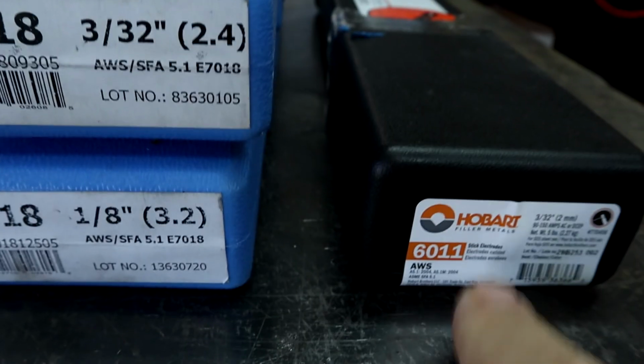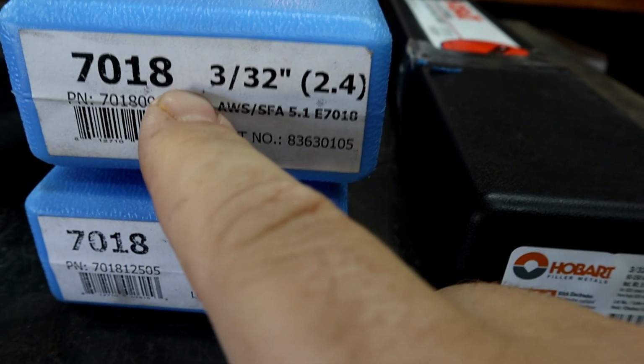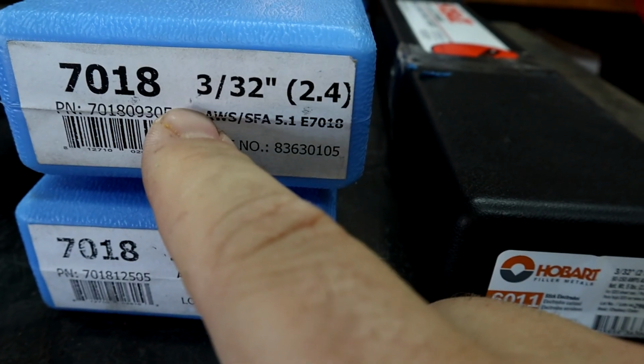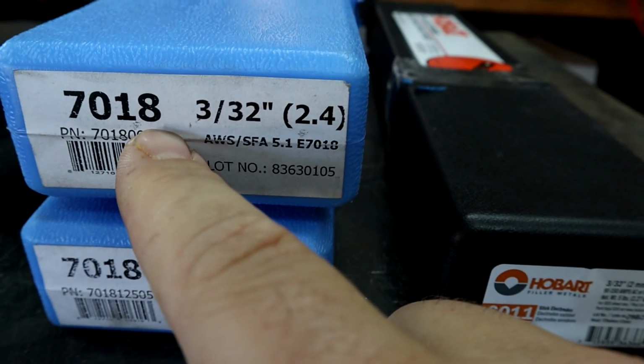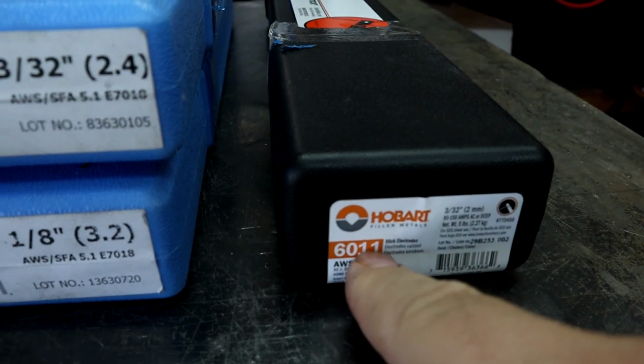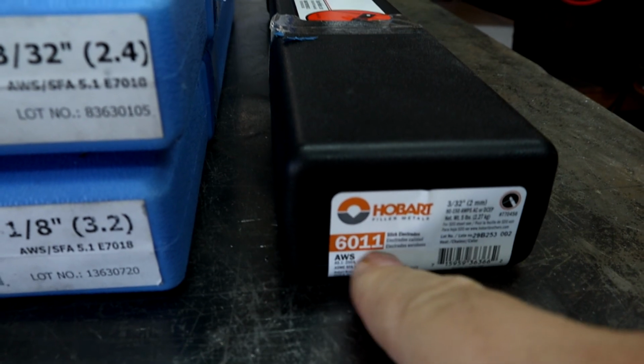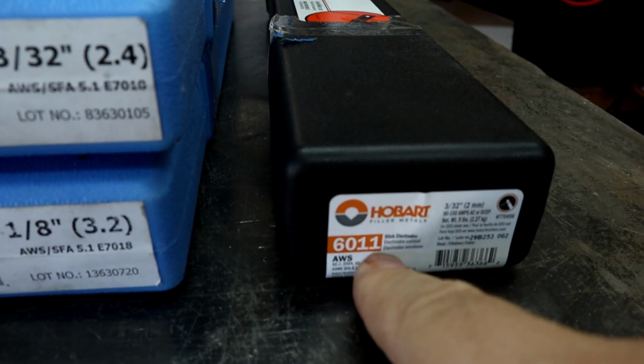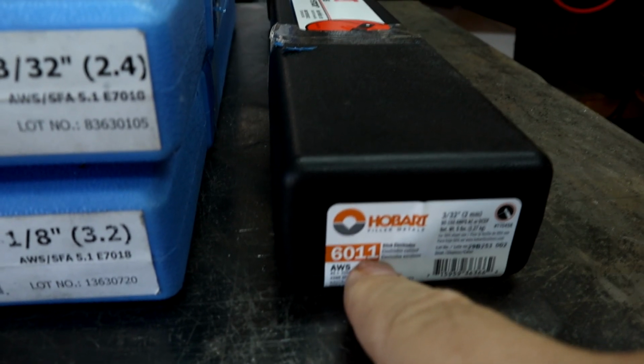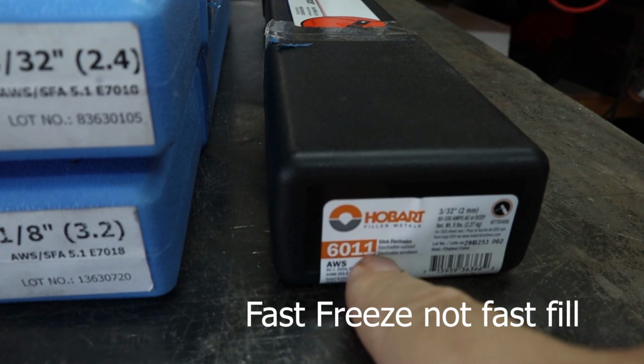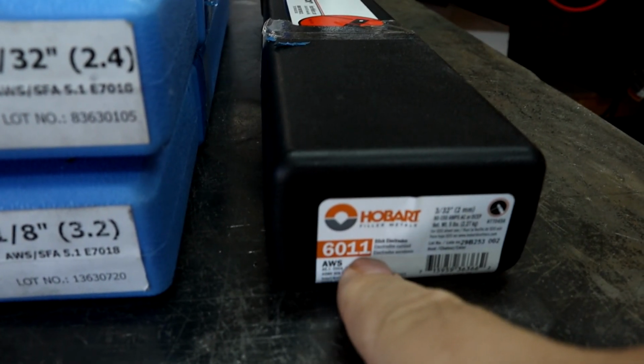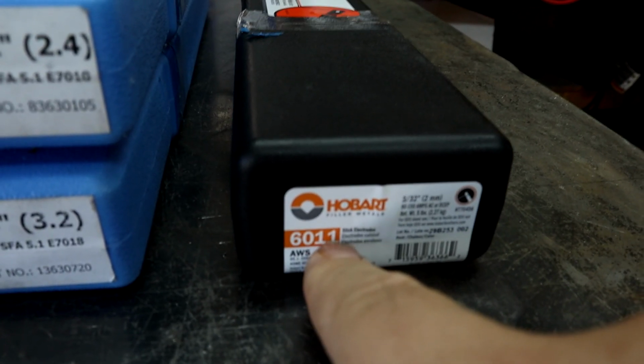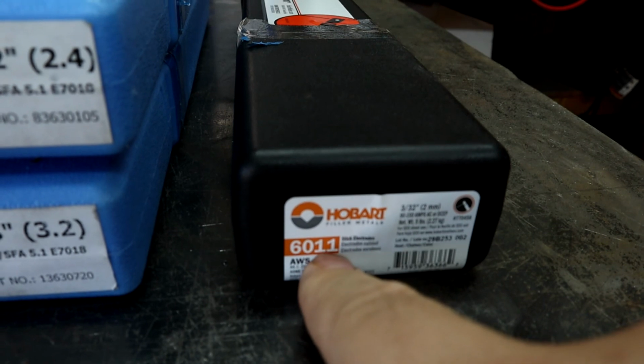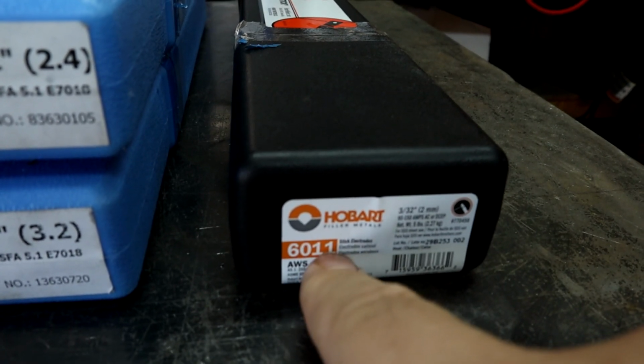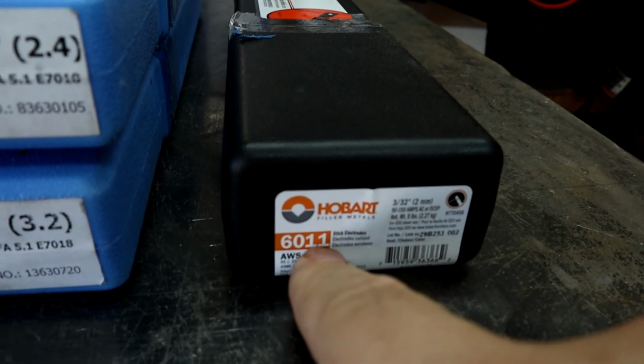And then the 8, or the 4th number in there, talks about the current characteristics and the flux coating on the electrode. In this case, anything that ends in a 5, 6, or 8 is considered to be a low hydrogen electrode. And then this one's a little different. So the 1 basically tells me that it's a deep penetrating electrode and a fast freeze, I believe. But it can be used with AC, and this is the difference between 6010 and 6011. The 6011 can be used with an AC current machine, whereas the 6010 you can do it, it just doesn't like it as well. So that's why I'm going with 6011 with this little machine as opposed to 6010.